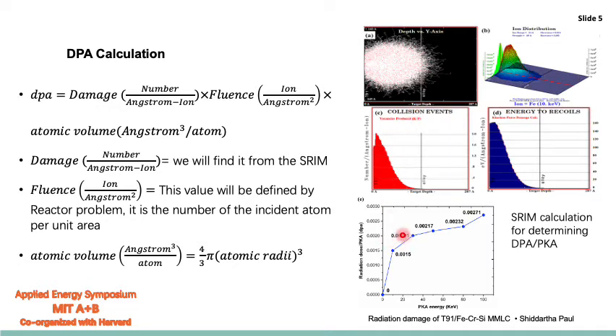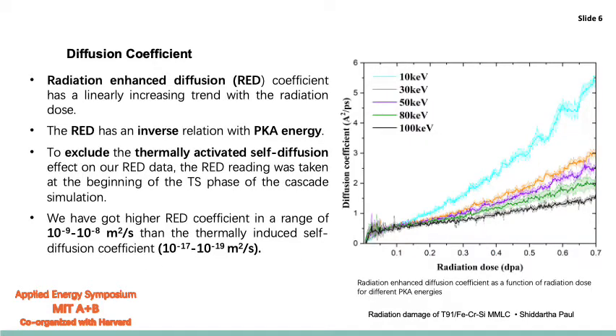So the calculated value we got for different primary knock-on atom energy has been shown in figure E, and we can see they actually have a kind of linear relationship with the primary knock-on atom energy. For the lowest primary knock-on atom energy we got 0.0015, and for the highest it was 0.00271. So in the figure we can see a linear increasing trend of radiation enhanced diffusion coefficient with the radiation dose.